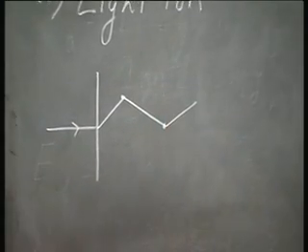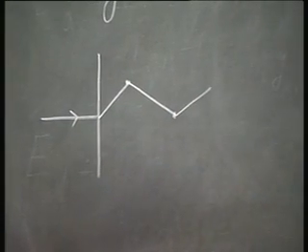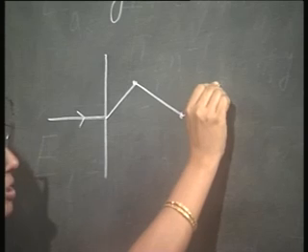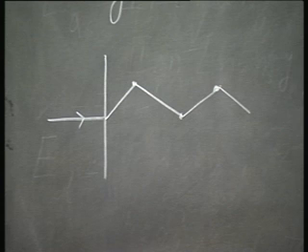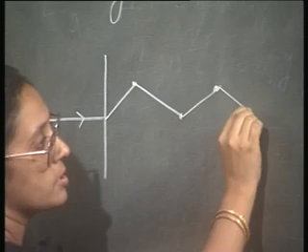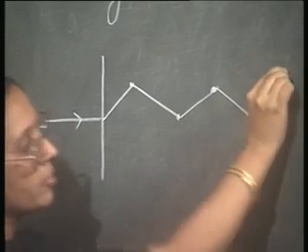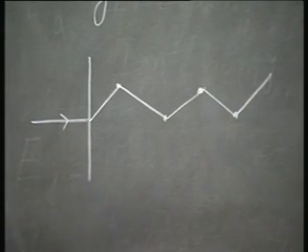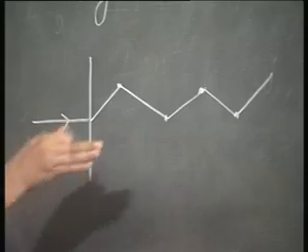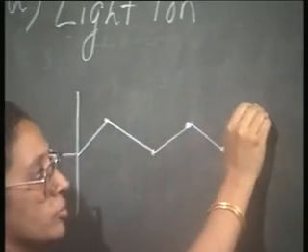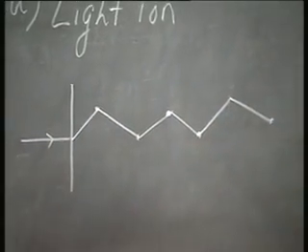Again it gets deflected by a large angle, and the process continues. And at each collision, since it is transferring a relatively smaller amount of energy, it is moving through a considerable distance before coming to rest. So, what you see is actually a long narrow branch of damage.